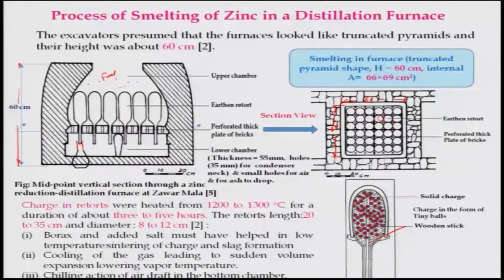And as I told, the borax and added salt must have helped in low temperature sintering of charge and slag, and the cooling of gas led to sudden volume expansion, lowering the vapor temperature. The chilling action of the air draft in the bottom chamber might have occurred due to this sudden volume expansion. Through these passages, ash and other things will come, and also some air will move in for the combustion of this fuel, which will be in this place.